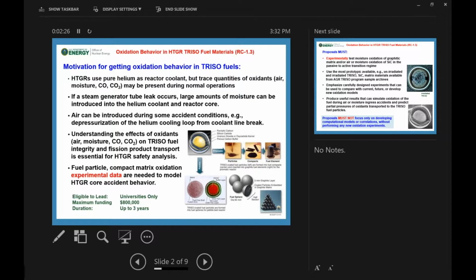So these fuel particles act as their own containment. They can either be put into compacts, and you'll see that on the side, and into fuel blocks. The compacts hold the particles together with something that is called matrix, which is a graphitic material. It has some resins, and that's what we mean by matrix. The alternative shape of these are in pebbles, where we have a fuel region where we use the same matrix, and then we have an unfueled zone that is also made up of matrix, and they're made into 60 millimeter fuel spheres. They're about the size of a tennis ball.